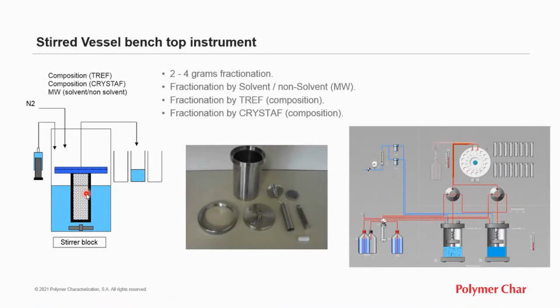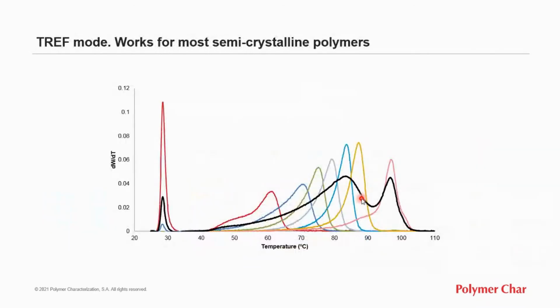In the first preparative system, the fractionation takes place in a stirred vessel with no support. In fact, in the instrument, there are two vessels, so two samples can be fractionated simultaneously. The amount should be lower than 2 grams per vessel. It can work both in TREF and Crystaf modes for chemical composition, but also by mixtures of solvent and non-solvent for molar mass fractionation.